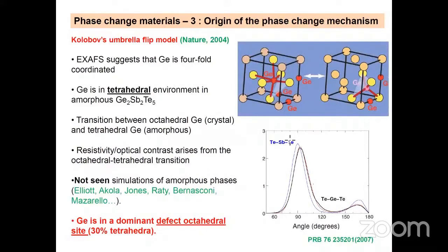So there is one very fascinating model which comes from Kolobov, who suggested that actually the difference in contrast arises from a difference in local geometry. That is, between the crystalline GST that you can see on this left figure, which is octahedral, and the amorphous one, there is just a simple switch from something which is octahedral to something which is a tetrahedral germanium. And so the suggestion, the main conclusion was that germanium should be tetrahedral in amorphous GST. And basically that everything relies on a transition between octahedral Ge in the crystal and tetrahedral Ge in the amorphous system. However, this typical feature was not seen in simulations.